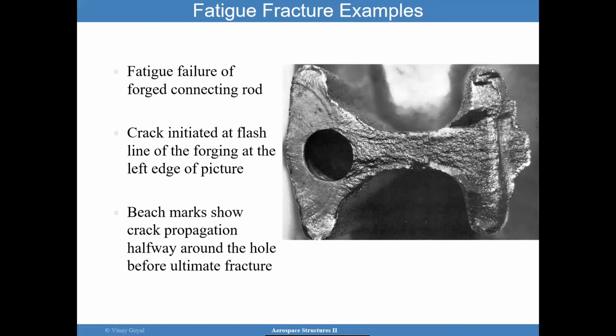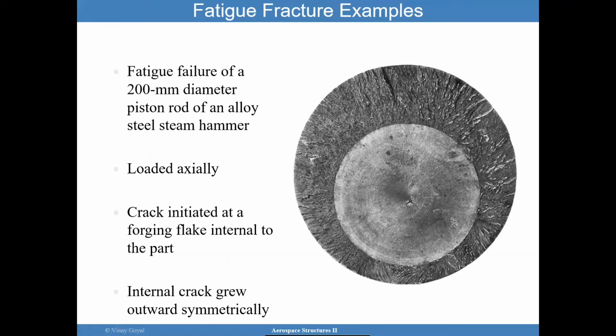You also have fatigue failure of a forged connecting rod. The crack initiated at a flash line of the forging at the left edge of the picture. And you can see some of the marks here. And the beach marks are these marks, showing crack propagation halfway around the hole before ultimate fracture. And this is your ultimate fracture right here. I think you're suddenly starting to understand how this works.